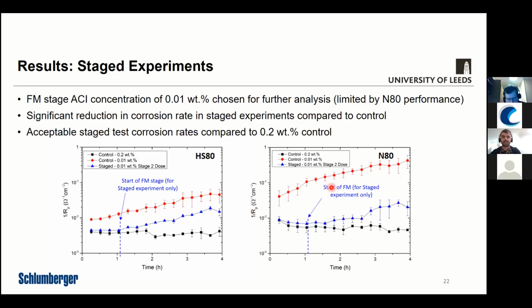This is even more dramatic for N80, where at 0.01% for the control experiment, inhibition efficiency was quite poor and corrosion rates were quite extreme by the end of the experiment. But again, that film forming stage was able to provide a persistent enough film that could be maintained with a much lower concentration of inhibitor. And the difference compared to continuing with the 0.2 weight percent film is not necessarily sufficient to justify the increased concentration throughout the entire experiment. So reducing the inhibitor concentration during the film maintenance stage is particularly effective and significantly reduces the corrosion inhibitor consumption as well.